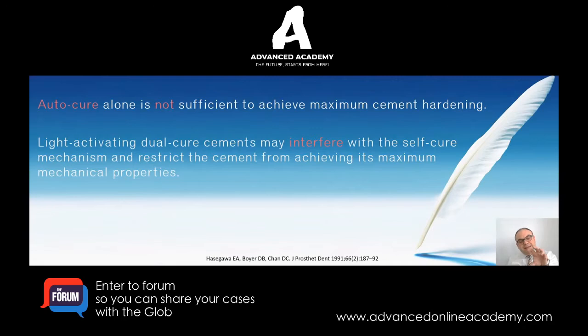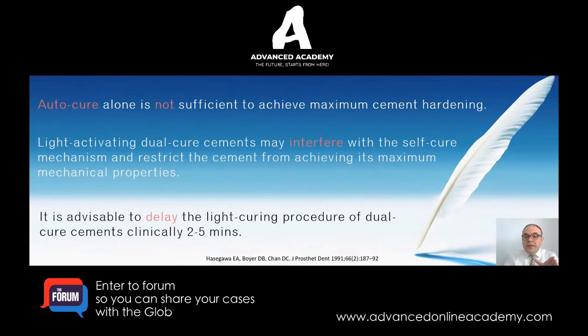We wanted to give the chemical component of the cement its time to set or to work before hitting it with the light. So what we came out with as a recommendation is that it is advisable to delay the light curing procedure of the dual cure cement by 5 minutes. Okay, so when you're using a dual cure cement, place your restoration, take your time.